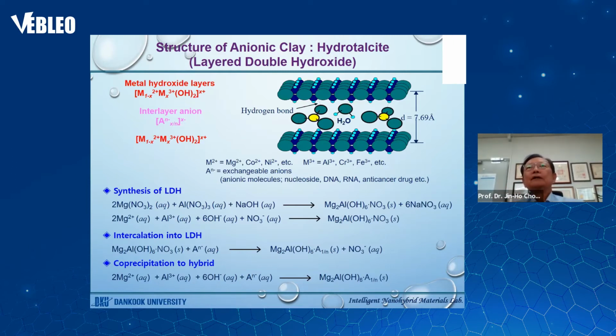In such a way, the positive layer charge can be generated. In order to compensate the positive layer charge, interlayer anions can be stabilized in between the hydroxide layers. Therefore, negatively charged drug molecules can be encapsulated into this lamellar structure by simple ion exchange reactions.